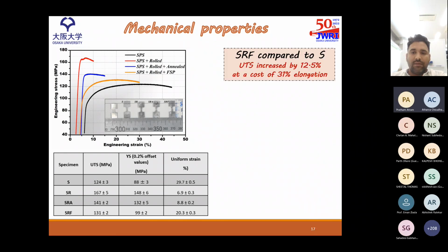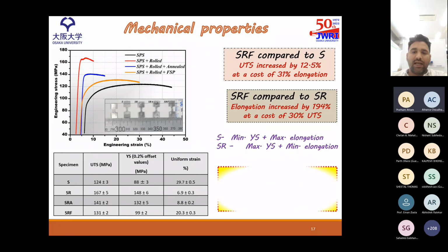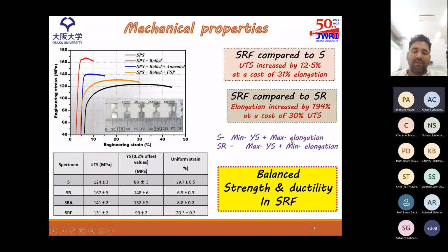And we can say that the minimum yield strength and maximum elongation is obtained by spark plasma sintering, but with rolling, we get the maximum yield strength and minimum elongation. So a balanced strength and ductility combination is achieved in SRF.